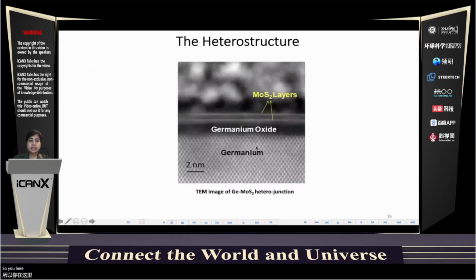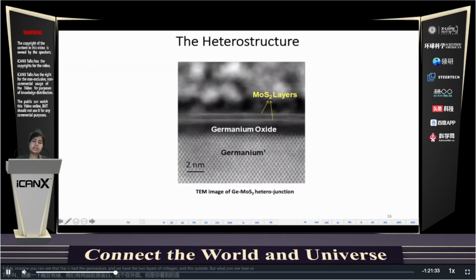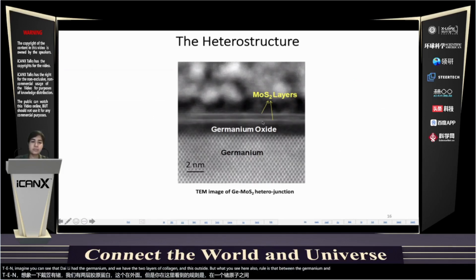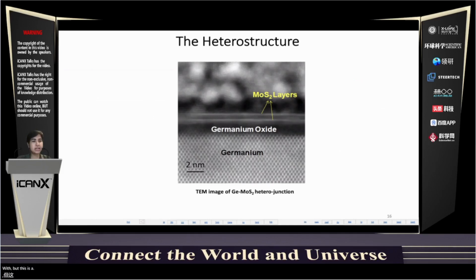So here is the TEM image, and you can see that we have the germanium and we have the 2 layers of molybdenum disulfide. But what you see here also is that between the germanium and the molybdenum disulfide layer, there is a thin layer of germanium oxide. Now this is a challenge because anything in here would increase the tunneling barrier width. But it is also an opportunity, because in future designs, it will be possible to remove the germanium oxide and passivate the surface and then improve the tunneling current even further.